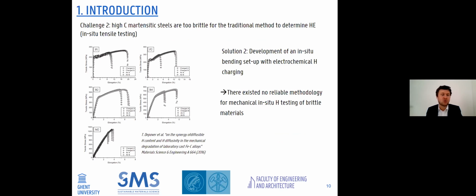A second challenge was that these high carbon martensitic steels are quite brittle. Normally we use in situ tensile testing to evaluate the sensitivity towards hydrogen embrittlement. As you could see here, this was in a previous publication from 2016. Here we compared different generic materials containing pearlite, ferrite, but also bainite, and we compared two different carbon contents.